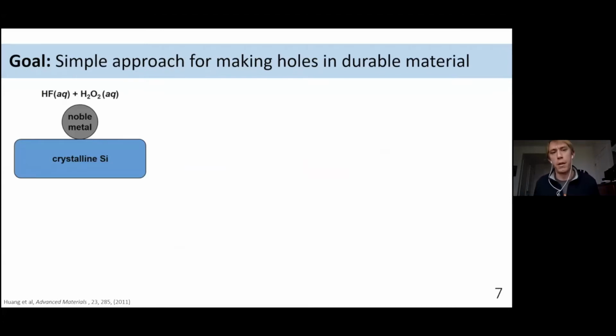So we did identify this gap in the upper right-hand corner of that plot I showed previously. And so our goal then became, how can we take a material that's intrinsically durable in order to fulfill that y-axis requirement of the landscape, and then poke small holes in it essentially to fulfill the filtration performance requirement? And can we do this at sufficient resolution and with sufficient control to go down to, say, the nanofiltration landscape, where we can access these small molecules, divalent salts, heavy metals, etc.?